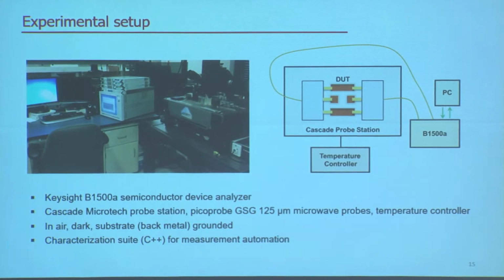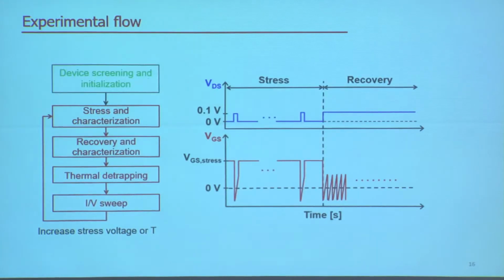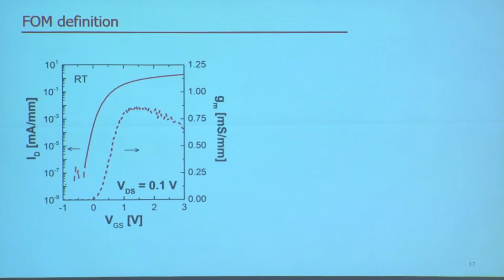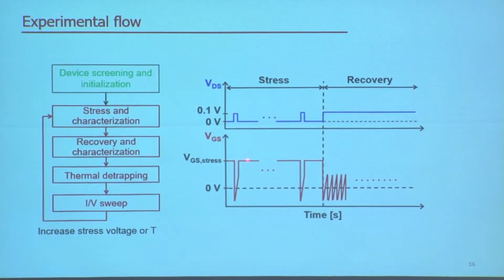Our group has developed a characterization suite in C++ to automate most of our experimental work. So here is the experimental flow. We start from device screening and initialization. In this step, we also extract very important device figures of merit, and they serve as a reference for the rest of the stress and recovery experiments. And then we apply a constant DC bias stress on the gate. During this period, we pause the stress periodically and perform a very benign short IV sweep to extract device figures of merit, basically tracing how they change during the stress period. After the removal of stress, we continue to monitor the change of device figures of merit for a period of time to look at how they recover.